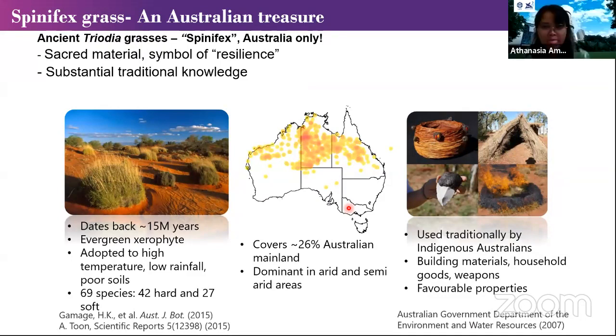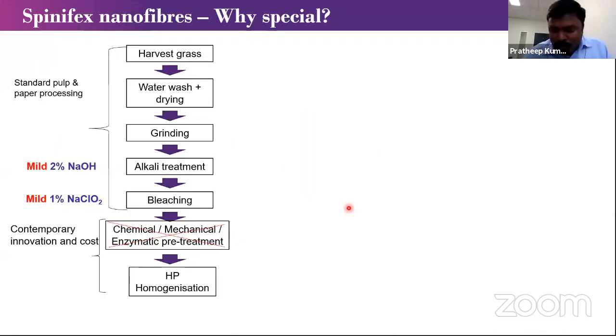And until I think 2008, it was not explored in terms of material science. So we had a PhD student and she looked into exploring this biomass. Because I come from a nanocellulose background, we tried to make nanocellulose in the same way that we can make from other sources. You can take the grass, wash, grind, make a powder, treat with sodium hydroxide and maybe bleach it. I mentioned the three types of nanofibers. When you want to make really thinner ones, you have to do some chemical modifications or enzymatic treatments. But for this source, you don't need to do that. So you can skip any chemical treatment, which reduces the cost and everything.